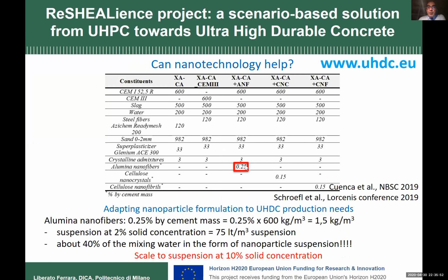0.25% by weight of cement for the alumina nanofibers, for example, and 0.15% by weight of cement for the cellulose products. What does that mean? 0.25% by weight of cement times 600 kilos of cement per cubic meter means we need 1.5 kilos per cubic meter of alumina nanofibers. Seems a very low quantity.